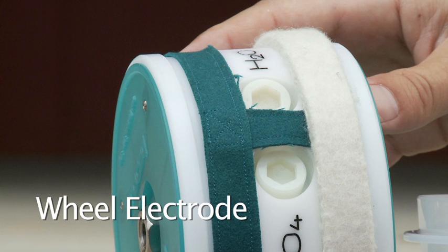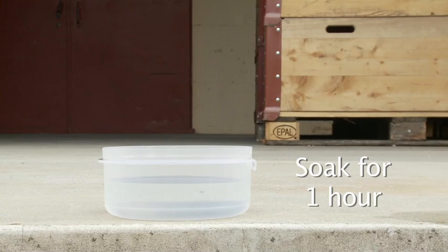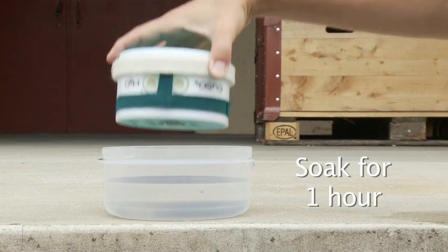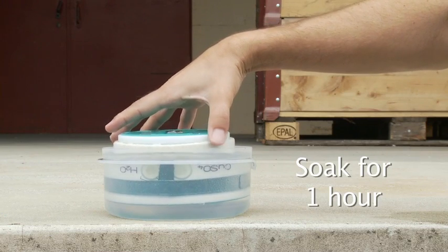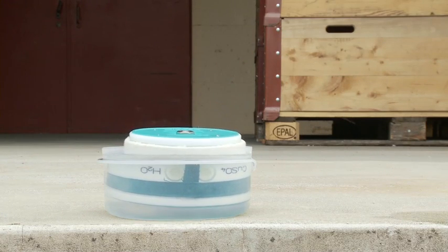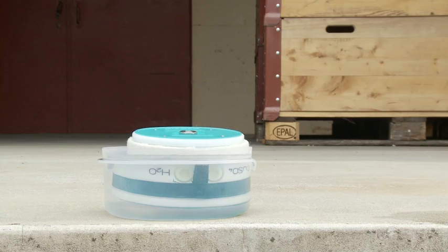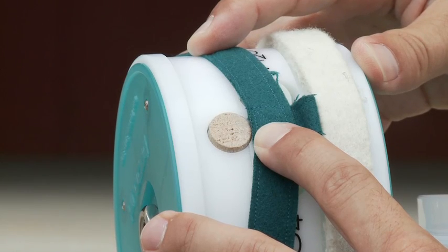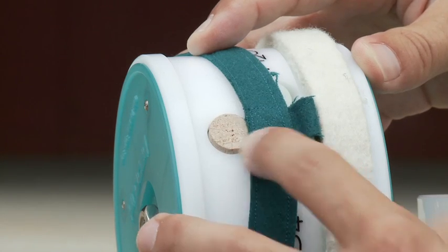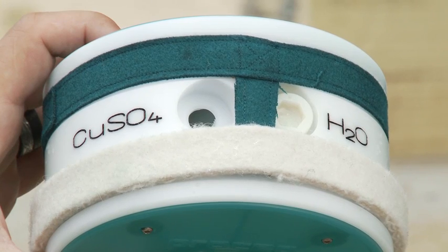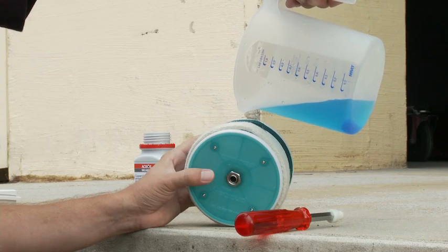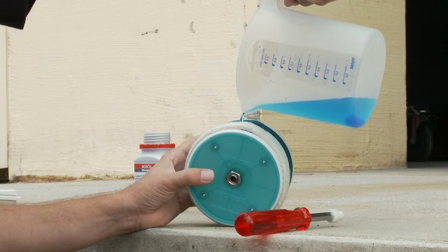To prepare the wheel electrode, soak it in water for 1 hour. The wooden plug is not intended to be removed. Immerse the wheel in water well before you intend to use it to allow water to soak into the plug. The felt hoops and the felt hoop connector should be saturated with water to ensure a low resistivity contact before measuring. The electrode should be filled as completely as possible with a minimum of air in the compartment.